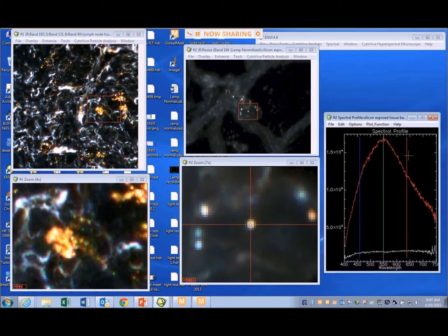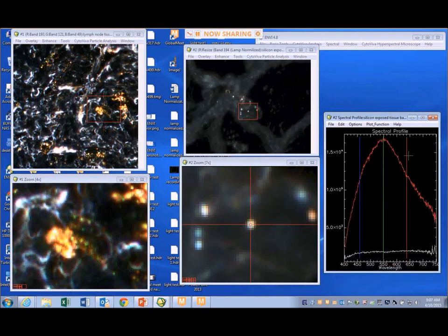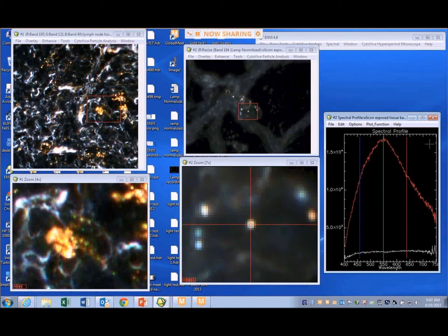Fibers are a little bit different than these generally circular nanomaterials. They actually embed in the tissue and you can see them on different focal planes. We have a couple of different algorithms for evaluating nanomaterials in the tissue. One is where you collect reference spectra — very similar to the red spectra you see in the spectral profile — and then map spectral profiles directly. Another is a peak location classifier, where you can use reference peaks and intensities to evaluate where the nanomaterials are. Those intensities also allow you to look at depth, because as the material becomes more deeply embedded in the tissue, it's less able to scatter light.